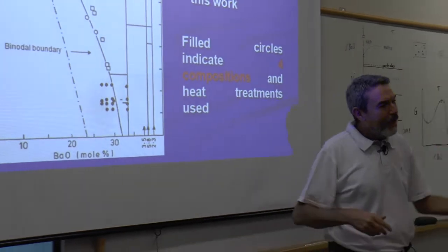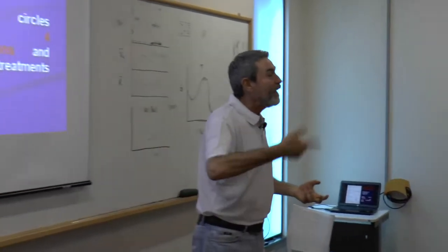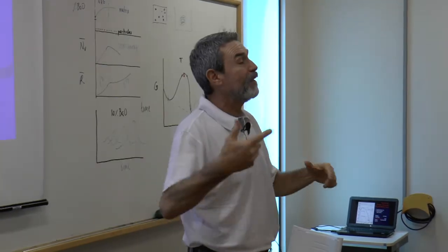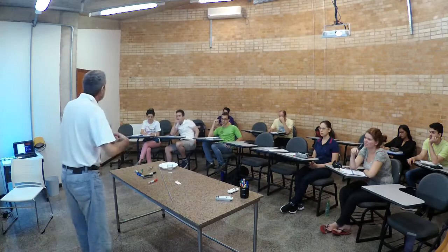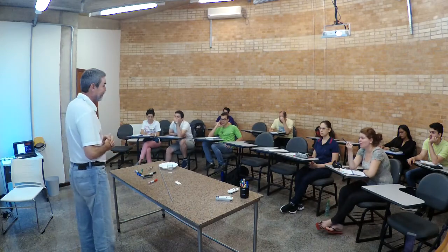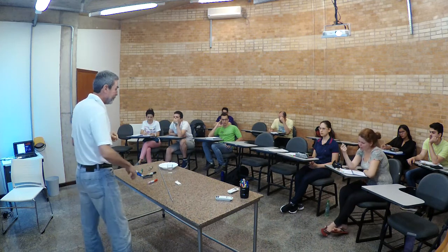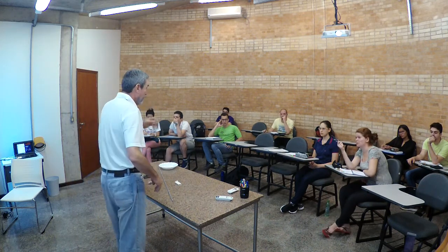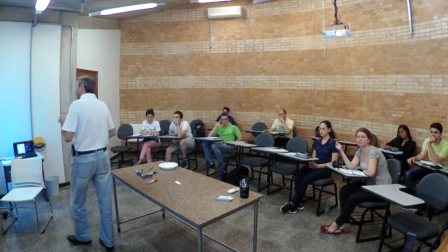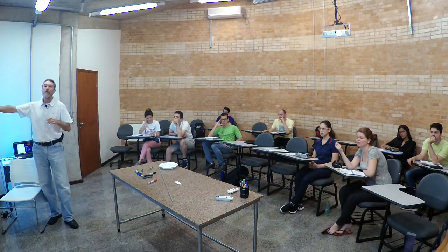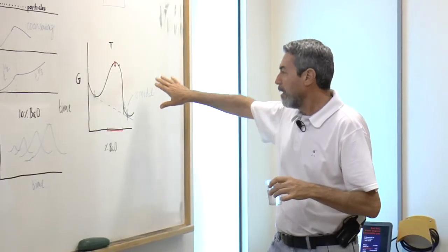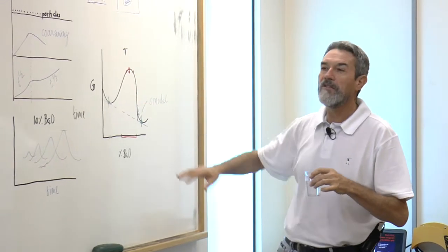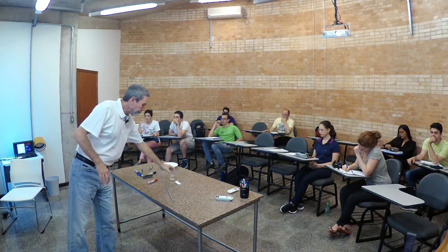Because you have liquid-liquid phase separation and crystal nucleation always taking place simultaneously. I did not talk about crystal nucleation yet, but things happen at the same time. But after the binodal boundary, the free energy increases as well. Well, after the binodal boundary, it's a single phase system. Then it increases, but it's a single phase system. It's only one glass.